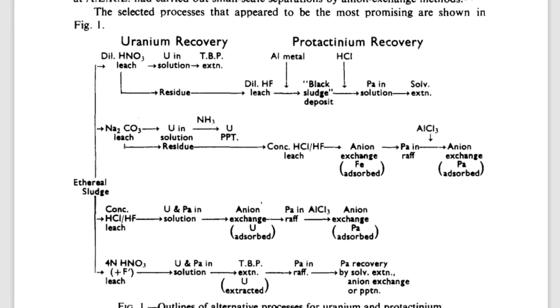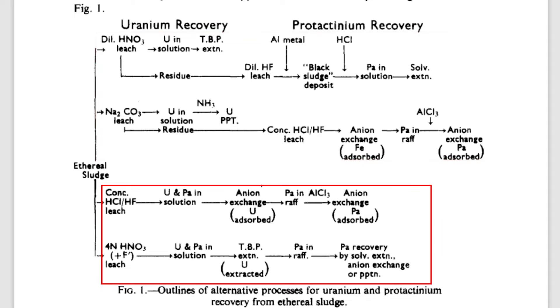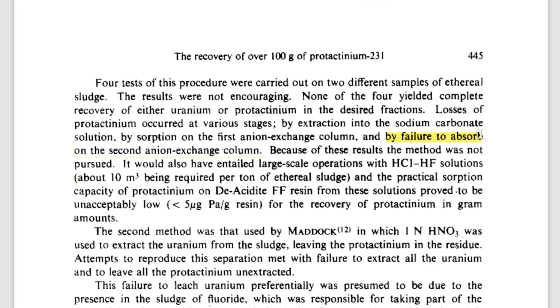There were several methods — four of them — which sounded promising. Two involved dissolving uranium and leaving protactinium behind; the other two involved leaching both and then separating the uranium. It was decided to dissolve the uranium and then follow protactinium processing methods. The Maddock method seemed unusable because protactinium was lost pretty much everywhere — for example, it didn't stick to the second ion exchange column. In general, it wasn't suitable for larger quantities because you would need 600 liters of hydrochloric-hydrofluoric acid for the setup.